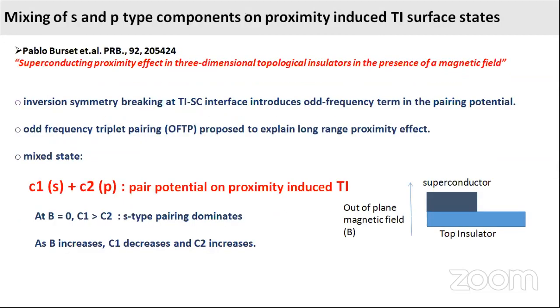Okay, so the main results of Pablo Burset's paper are that when there is an interface between a topological insulator and a superconductor, there is a breaking of inversion symmetry, and such a breaking of inversion symmetry in this kind of hybrid structure could cause an additional pairing term in the superconducting pairing, which is an odd frequency triplet pairing. Generally, the pairing is of even frequency nature, but because of the breaking in the inversion symmetry, there is an odd frequency term that gets introduced. And what's very interesting about this odd frequency term is that it has been proposed to explain long range proximity effects, particularly in superconductor and ferromagnet hybrids. So such is the kind of state that we can expect.